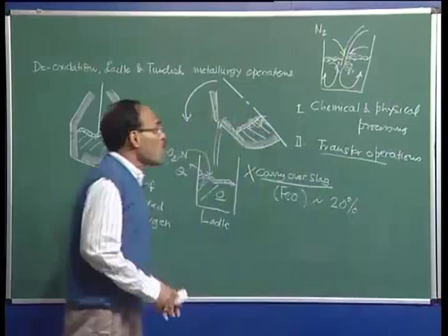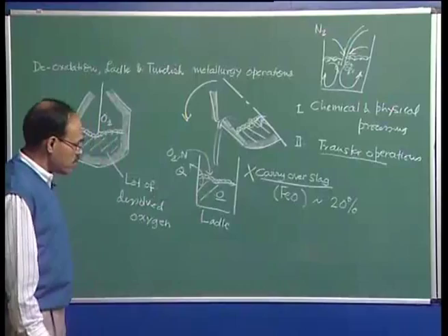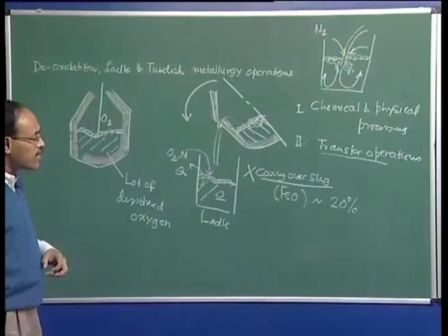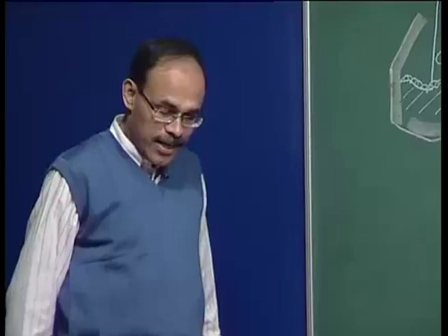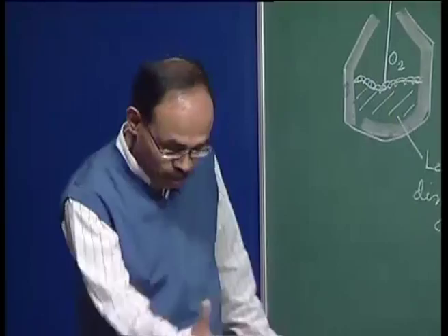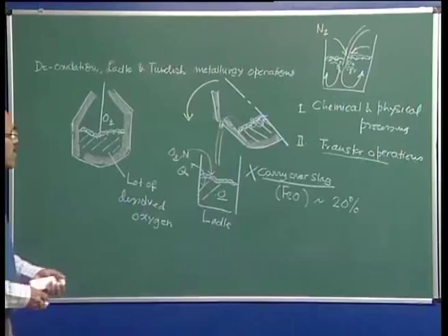So, we must understand that during the tapping operation, an extremely intense hydrodynamic stirring is available in the bath itself. Now, if you are going to add some elements which react with the oxygen in order to take the oxygen away from the bath, those elements can melt and dissolve in steel very quickly. For example, if you add a drop of potassium permanganate in that bucket, on which you can do an experiment in a bathroom, you can see that the potassium permanganate will dissolve in the bucket of water very rapidly, and the same happens in the steel making ladle during the furnace tapping operation.